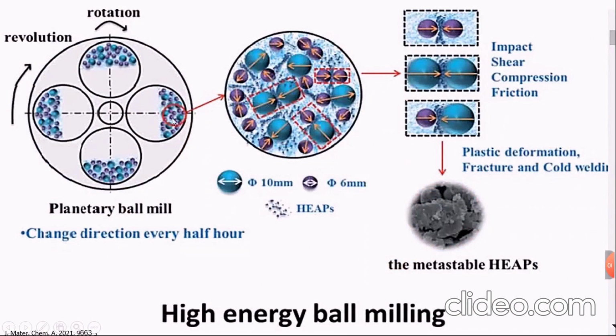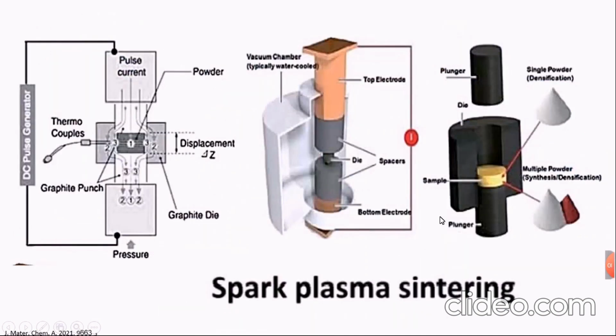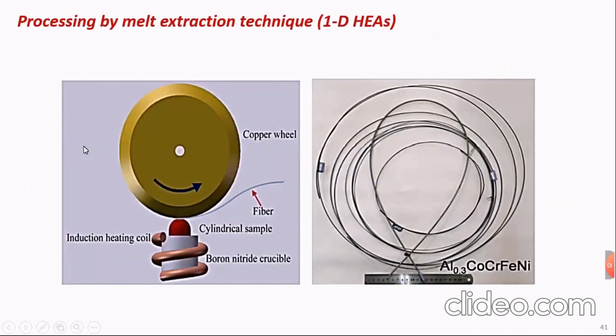And another type, the planetary ball mill. In this type, the direction of rotation is changed every half an hour. So you have the particles strike together, we have impact, shear, compression, friction, then you have plastic deformation, fracture and cold welding. This is a metastable high entropy alloy produced by high energy ball milling. Also, spark plasma sintering is one of the known techniques to produce high entropy alloy discs, for example. And this is a high entropy alloy produced from multiple powders by synthesis and densification.